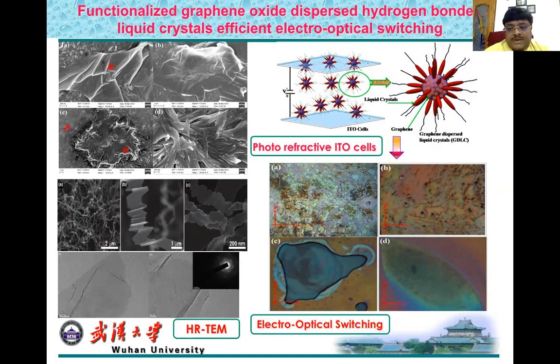liquid crystal based graphene oxide we put into our photoreflective ITO cells, and we looked at how it reacts under a polarizing optical microscope. You can see some platelet-like structure and then a marble pattern. You can see the honeycomb structure evolve with several applied temperatures, and it depends, of course, on the liquid crystals, because we use thermotropic liquid crystals.